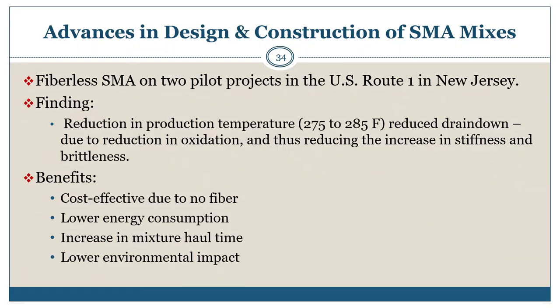There have been studies comparing projects between a standard SMA mixture and then making reductions either in terms of asphalt content, removing fibers, removing the polymer modified asphalt on adjacent sections to determine the difference in performance as well as the difference in cost between projects defined as SMA and other mixtures that are called SMA mixtures but not designed to the strict requirements as previously mentioned during this presentation.